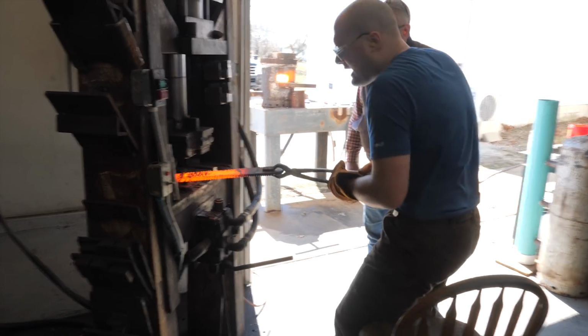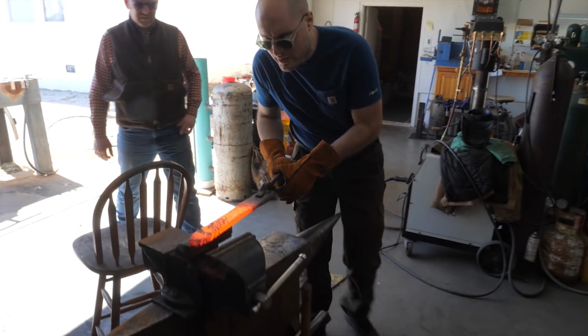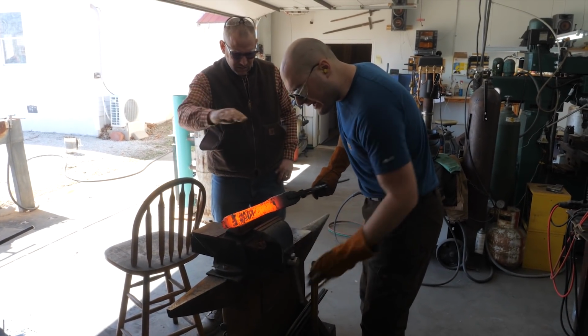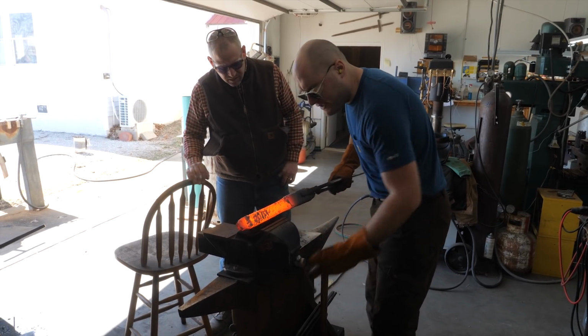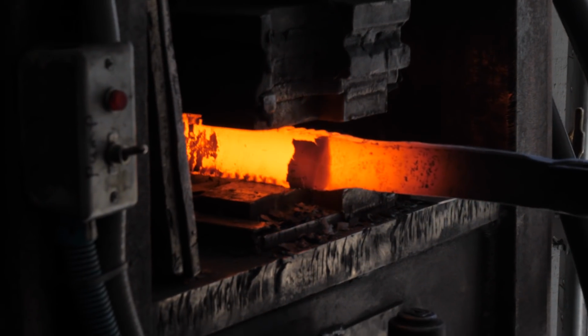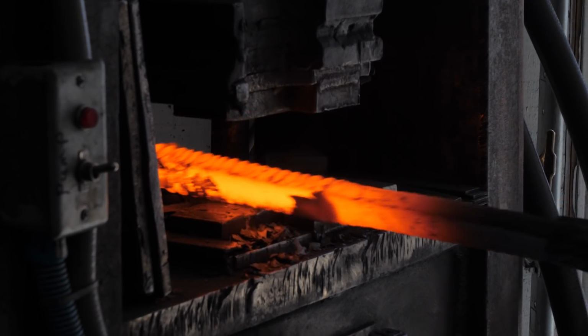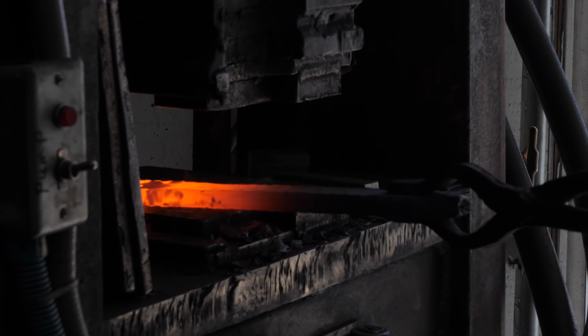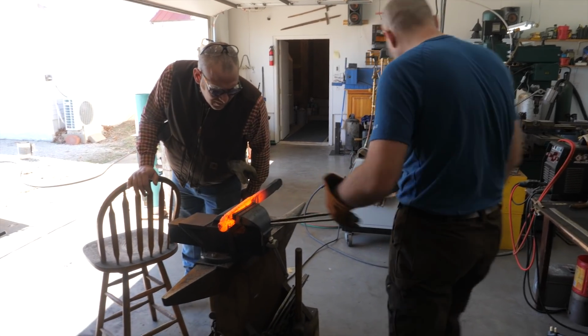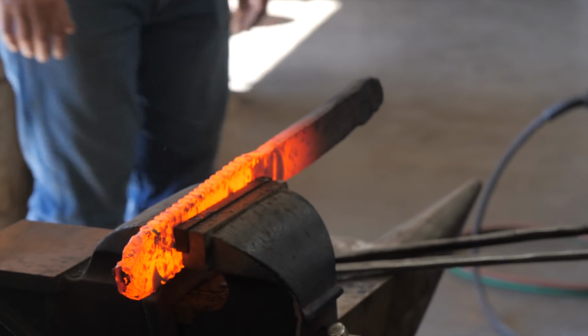Go ahead and grind the edges a little bit, and I'll flip it around and do the other end. Bevel the edges, or just grind them? I'm going to try to grind some of the spots that sheared out of the edge, clean this up a little bit. There's some shears in the billet. It made me have to make it a little bit narrower than I wanted. Alternate to keep it square. Yeah, that's some bad shearing right there in the middle on both sides. That's why it's extra skinny right there.